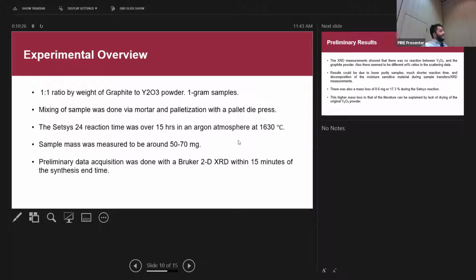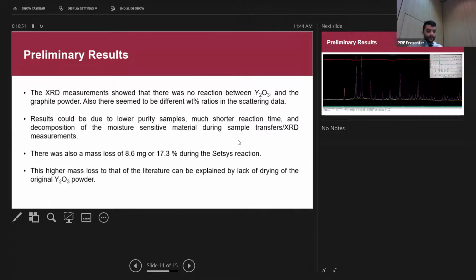And then the preliminary data acquisition was done in a Bruker 2D XRD within 15 minutes of the synthesis end time, because this material is moisture sensitive and it tends to decompose back into yttria after a while, if it spends too much time out in the moisture and whatnot. And that's why we employ glove boxes and desiccators.